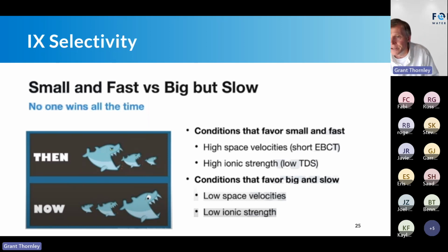I thought this was quite relevant: small and fast versus big and slow. So what does that mean? It means that certain conditions will favor a small ion and will work fast, meaning high space velocities or short empty bed contact time, meaning it's going to load very quickly, and high ionic strength in an environment of low TDS. And that favors the small ions with a fast load rate. Conditions that favor big and slow is when you have low space velocities and low ionic strength.